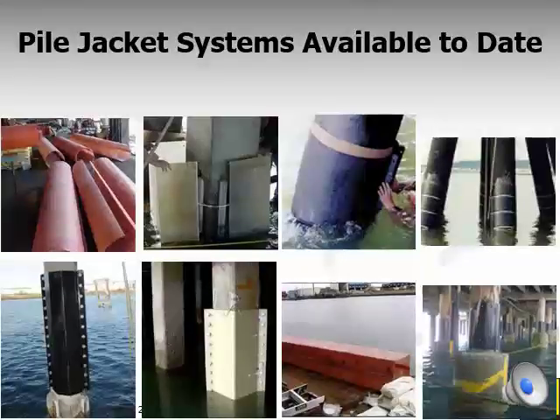This causes a lot of delay and added expense for the project, especially if you happen to get them in the wrong size. Secondly, the shipping of these products becomes very bulky, and it adds to the cost of shipping and storage. And thirdly, the way these shells are put together, there are one or two seams along the vertical leg of these shells, and that becomes the weak point. By nature, these shells cannot apply any confining pressure to the column, and from a structural engineering point of view that is a major weakness. Furthermore, these same seams allow moisture and oxygen to get into the jacket, and therefore they are not very effective in stopping or slowing down the corrosion process.